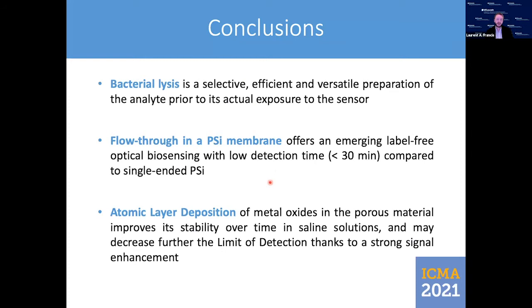As a conclusion, bacterial lysis is a selective, efficient, and versatile preparation of the analyte prior to its actual exposure to the sensor. The flow through in a porous silicon membrane offers an emerging label-free optical biosensing with low detection time below 30 minutes compared to single-ended porous silicon. And finally, atomic layer deposition of metal oxides in the porous material improves its stability over time in saline solutions and may decrease further the limit of detection thanks to a strong signal enhancement.